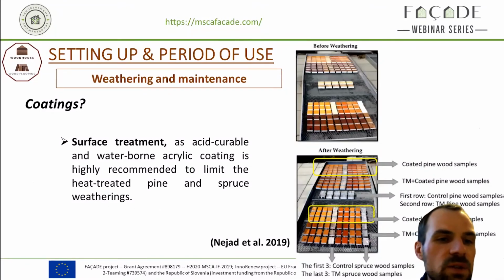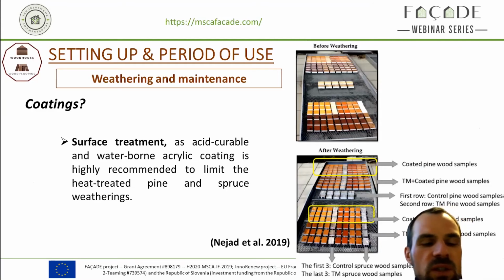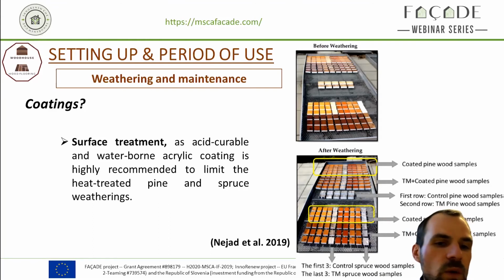The last aspect of the period of use of thermally modified wood concerns the weathering and the maintenance of the modified products. It results that heat treatment does not prevent the natural aging, weathering, and gray coloring of the wood during its service life. In this sense, some surface treatments such as acid curable or waterborne acrylic coating could be highly recommended to limit the heat treated wood weathering and gray coloring. Such maintenance and surface treatment need to be considered during the life cycle assessment of thermally modified wood products.